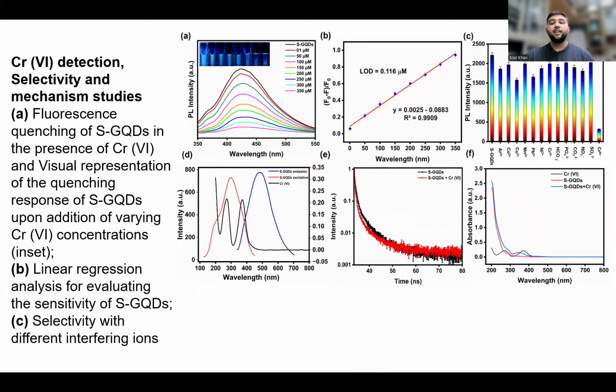Then we checked the mechanism of this quenching. There are different types of quenching mechanisms. For this we took the emission and excitation spectra of sulfur-doped graphene quantum dots, and then we checked the absorbance of chromium-VI. We can clearly see it is overlapping with the excitation of the sulfur-doped graphene quantum dots. So when the absorbance overlaps with the excitation of the fluorophore, then the mechanism will be the inner filter effect.